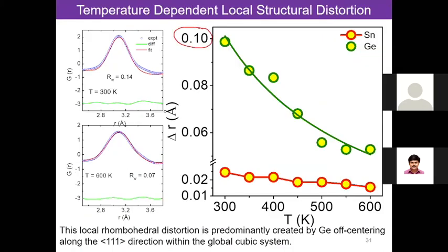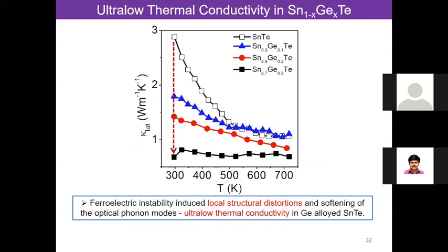That is 10% of a bond length, and that is quite huge actually to give a ferroelectric instability and low energy optical phonon modes, as you see from the calculation. And these give rise to extremely low thermal conductivity in this material.